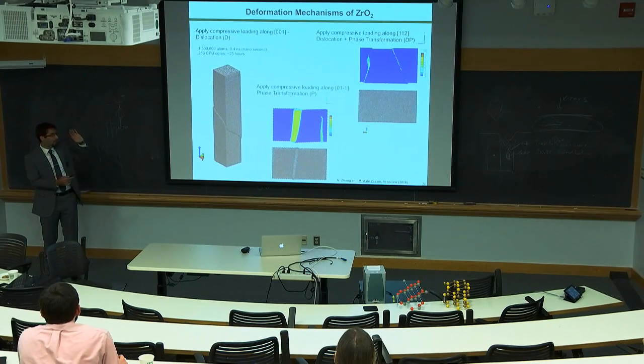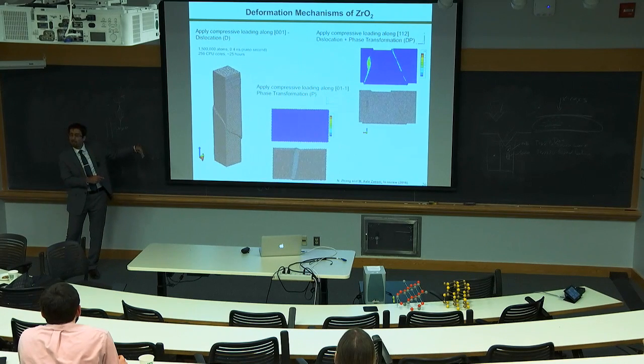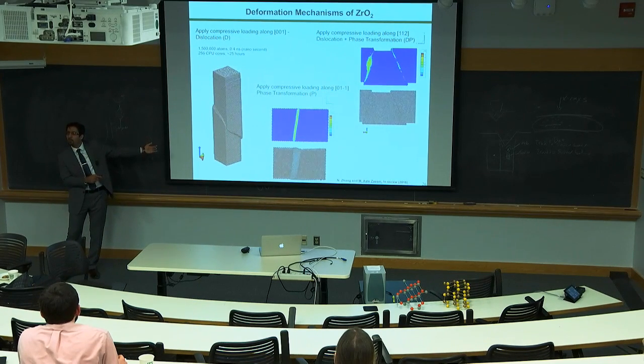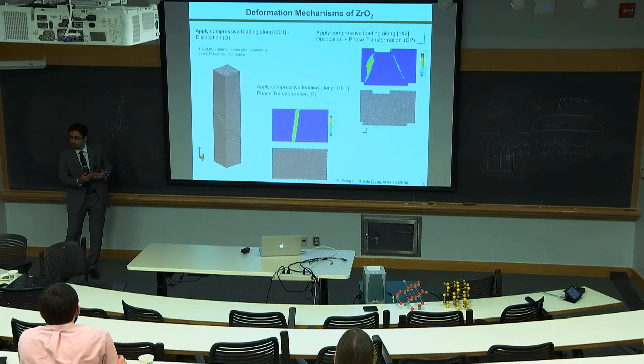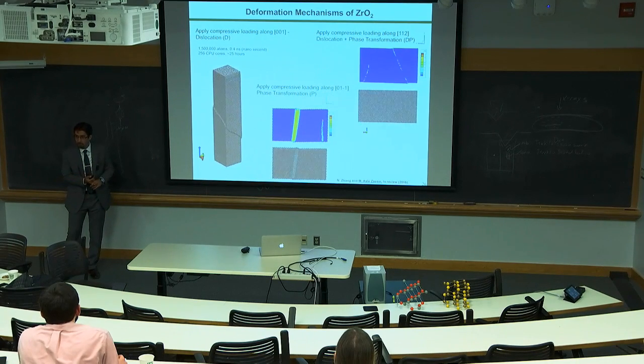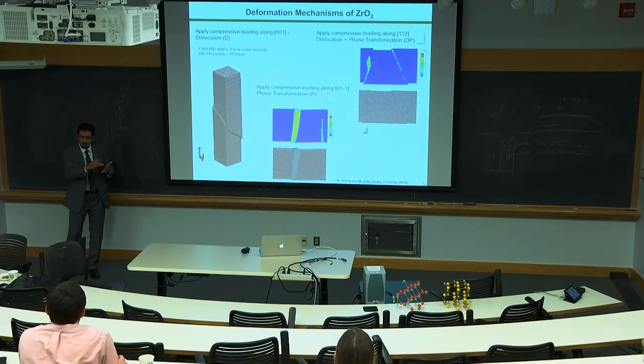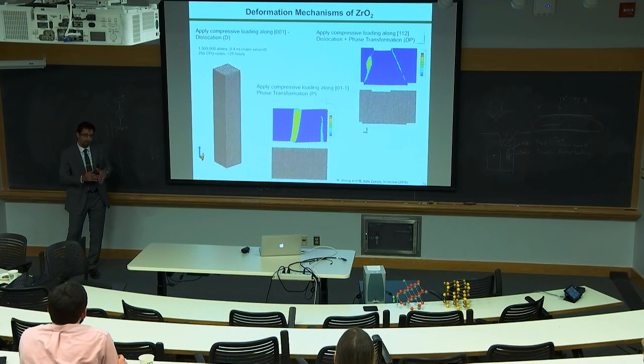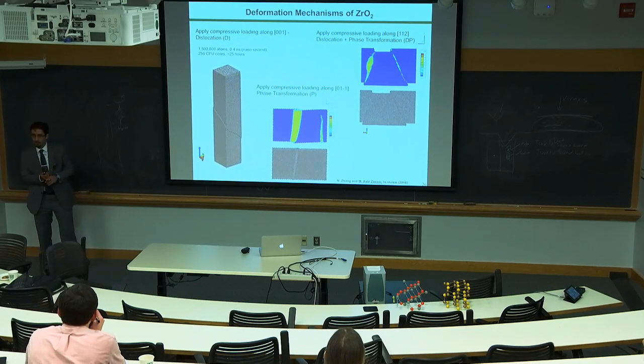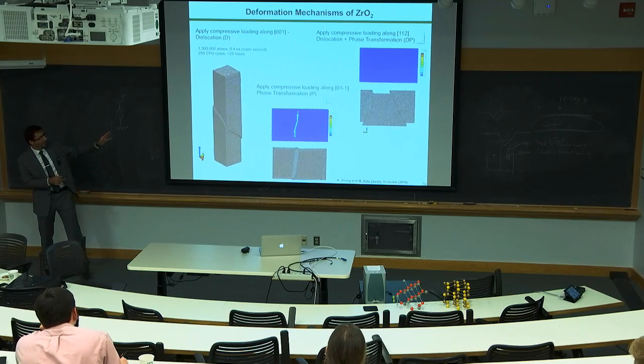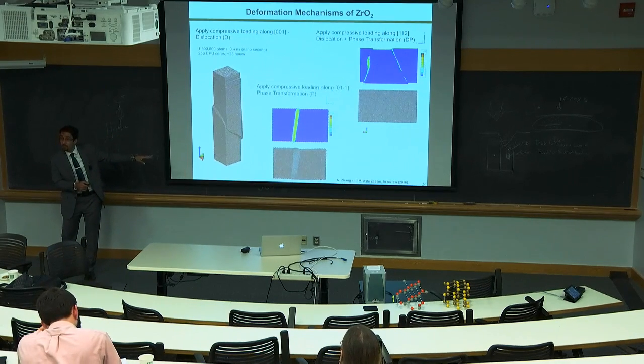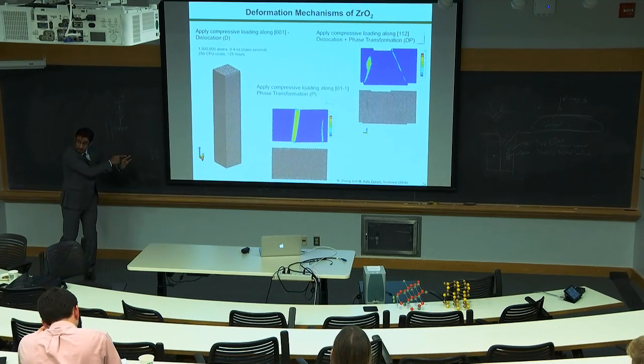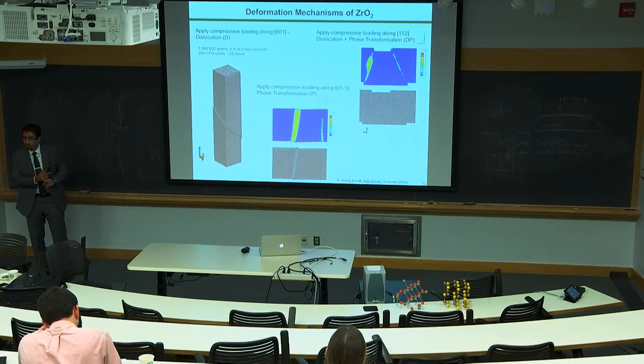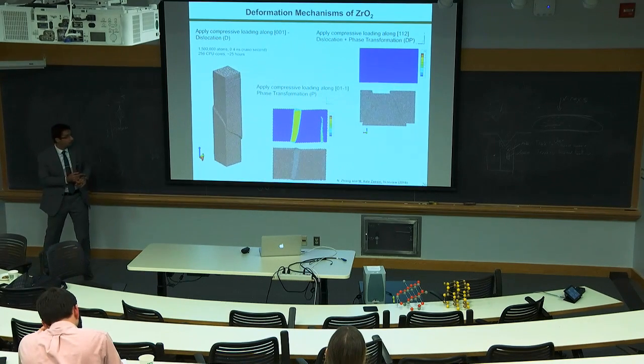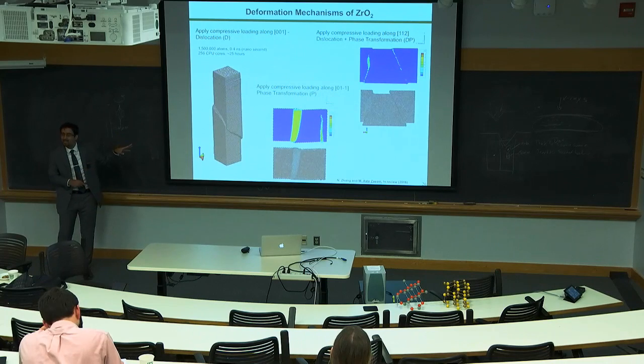First of all, one of the reasons is we usually cannot go more than 5 million atoms at a time, because then we cannot visualize it. We do not have a computer available to do that. So we stick with less than 5 million, and it would need really huge supercomputing. But if you go less than about 800,000 atoms for this case, the behavior will change. So we wanted to make it as close to the experiments as possible.